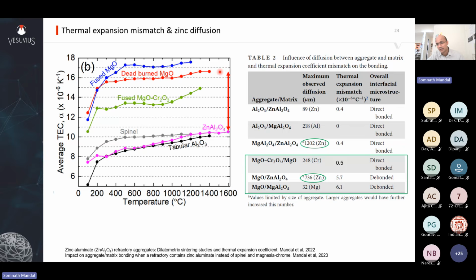That sort of difference is already there in your zinc aluminate, so you have the benefit of the debonding due to the TEC difference. What is missing is the solid solution formation that gives you the hot strength. You can get that from the zinc aluminate addition and combining it with magnesium aluminate. And it is applicable for iron oxide rich slag?